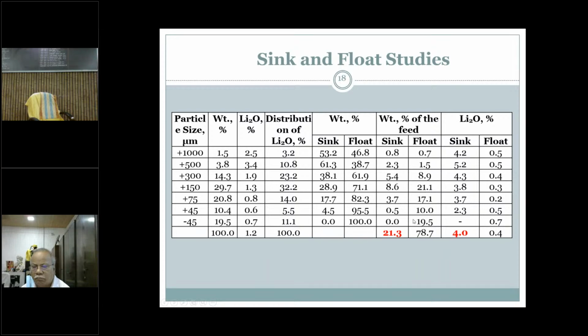On average, we can say that in case we subject the entire material to a density of about 2.89, using bromoform, the sink fraction will have a weight percentage of about 21.3 percent, and the float will have about 78.7, and these heavier fractions will be carrying the spodumene. It will be saying about 4.